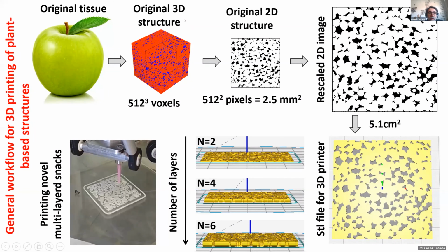From original tissue, we acquired the microtomographic image, and from this voxel, we extracted just one slice, 512 pixels. Then we rescaled from millimeter to centimeter, and this structure was used to create an STL file. This STL file was used to obtain different models, 2 layer, 4 layer, 6 layer, like crackers with a different thickness. And then we started to print to create something new. The second question is whether we will also be able to predict texture.